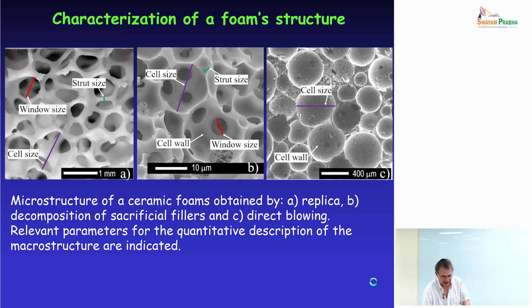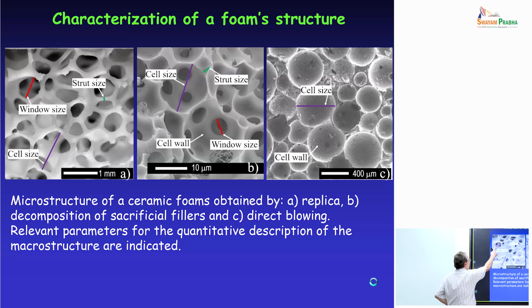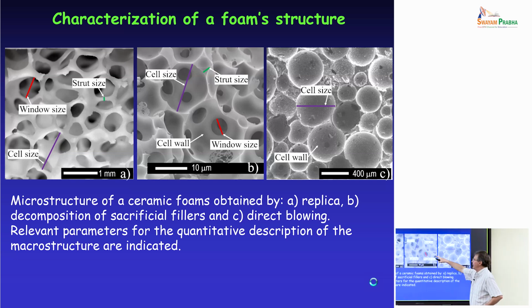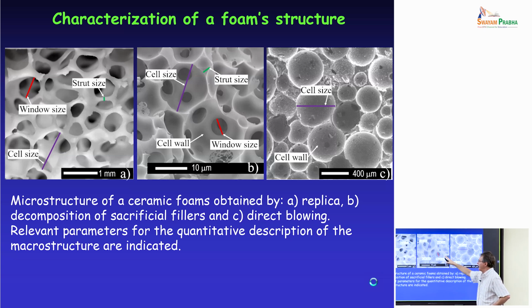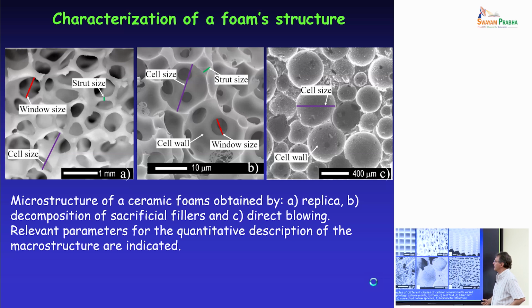And of course, if you have a cell and you have a cross section, you don't know in your structure where the fracture cut. So you get one size, but you do not know if it is the real diameter of the cell or not. And there are some stereological equations that allow you to convert the measurements from 2D to real 3D. You can find that in the literature. So you can quantify the cell size, and you can also quantify what is called the cell window size. And of course, you can have foams where you have fully closed cells, or you can have foams where you have a certain amount of porosity within a closed cell wall. So you need to be able to characterize all these features in your foam.